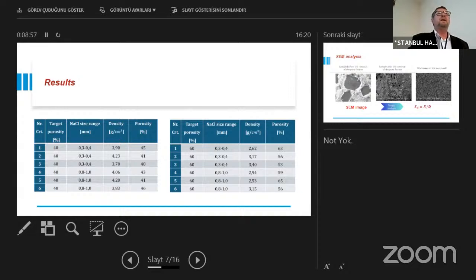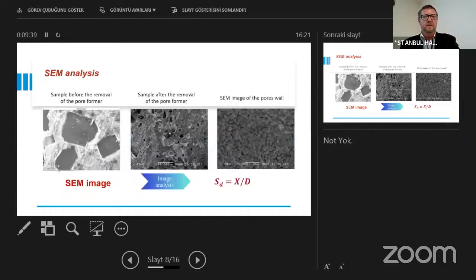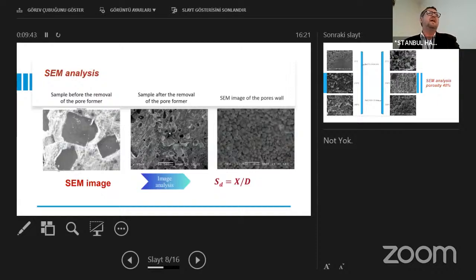We obtained porosities a little lower and higher than expected because, although we homogenized and calculated everything right, the density of the salt and the zinc is very different—almost 2 and 7 g/cm3. When we manipulated the powder mixture after homogenization, there was some separation. Also, in the porous walls there are inherent porosities given by the powder packing. So we had porosities close to the desired one. These variations are specific to this method, so nothing really unusual here.